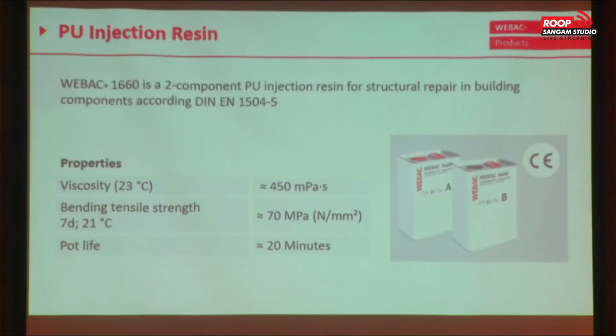This is one of the products, Webac 1660, I mentioned before, that you heard about: a polyurethane resin which develops a high bending tensile strength and a high strength development inside the crack. Here we speak about 70 megapascal, 70 Newton per square millimeter without any contact with water. Of course, it will slightly foam, and this minimizes the strength development, but at the end we are always higher than 35 or 40 Newton per square millimeter with a foamed product.